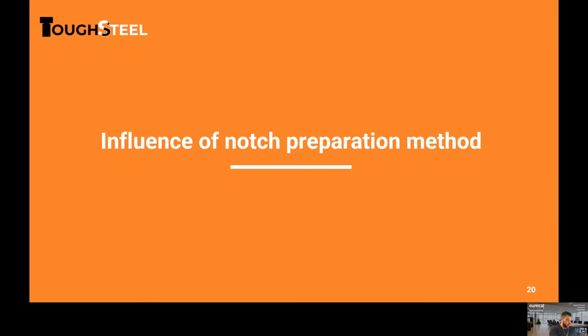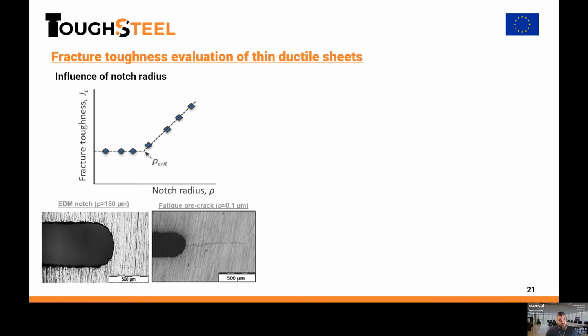Finally, to finish the presentation, one of the aspects to keep in mind when measuring fracture toughness is the influence of the notch preparation method, or the influence of the notch radius, for example. As is well known in fracture mechanics, fracture toughness, JC, essential work of fracture, depends on the notch radius until a critical notch radius is reached, below which the fracture toughness becomes independent of the notch radius. But if we want to measure accurate fracture toughness values, we need notches as sharp as possible, and see what the minimum possible radius is.